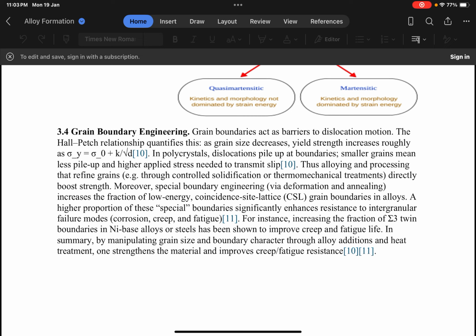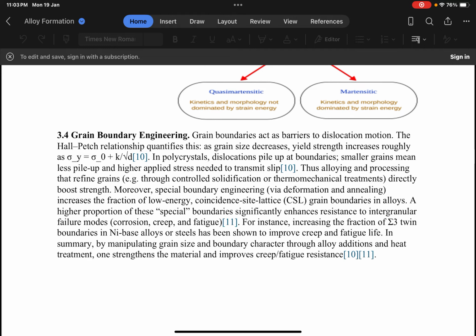Moreover, special boundary engineering via deformation and annealing increases the fraction of low energy coincidence site lattice, CSL, grain boundaries in alloys. A higher proportion of these special boundaries significantly enhances resistance to intergranular failure modes, that is corrosion, creep, and fatigue. For instance, increasing the fraction of sigma 3 twin boundaries in nickel-based alloys or steel has been shown to improve creep and fatigue life. In summary, by manipulating grain size and boundary character through alloy addition and heat treatment, one strengthens the material and